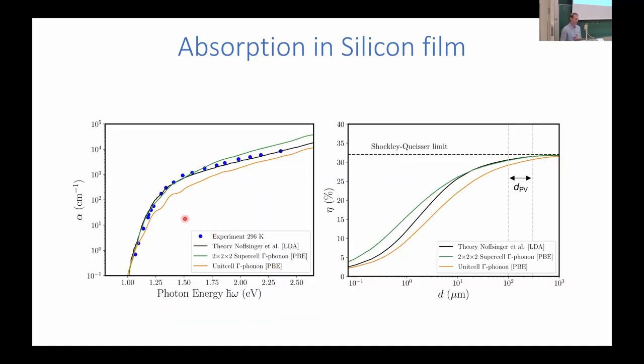As you can see, we already get pretty good results from the primitive unit cell. The blue dots are experimental values for the absorption coefficient of silicon — it starts at around 1 eV, which is the indirect band gap, while the direct gap is at 3 eV. With our gamma-point phonon approximation we get the orange line. When you convert this into a photovoltaic efficiency, it's close to the green curve which matches experiments, and is quite adequate particularly in the typical region for a thin film silicon solar cell.